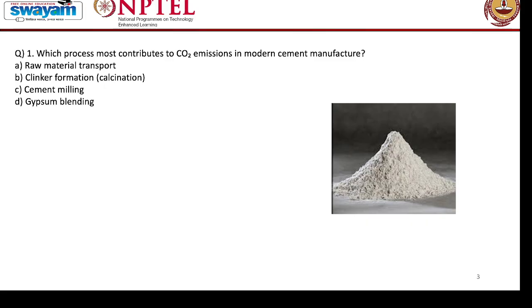Okay, let's see the answer for this question. The answer is B, clinker formation itself. The calcination reaction in the formation of clinker produces a lot of CO2, because the limestone breaks down and releases CO2 as a byproduct and forms the clinker. Hence, we can reduce CO2 from cement manufacture by using less clinker. The typical clinker requirement of an OPC system can be reduced by using replacements such as supplementary cementitious materials, to lower the use of clinker, because we need clinker for the hydration reaction to take place.